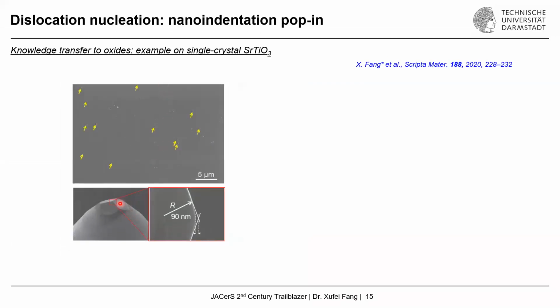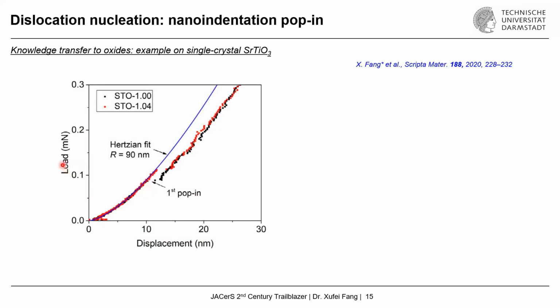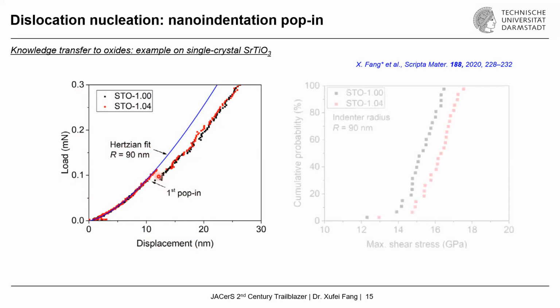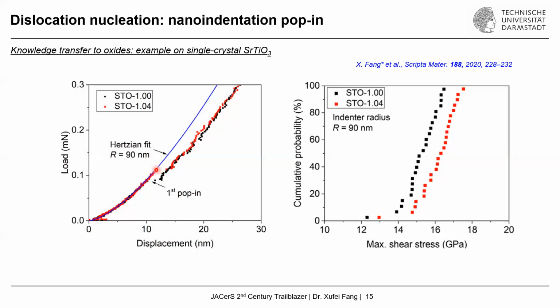That means if we are going to place a very sharp indenter, for example, with a tip radius of roughly 90 nanometer, we have an extremely high chance of putting the indenter into a dislocation-free region. What happens is that we see a similar load-displacement curve: first it deforms elastically, as can be captured by the Hertzian fit, and then all of a sudden you have a jump here. By computing the stress level corresponding to this event, we see also 14 to almost 18 gigapascal stress level, even for different strontium titanate samples with different stoichiometry.